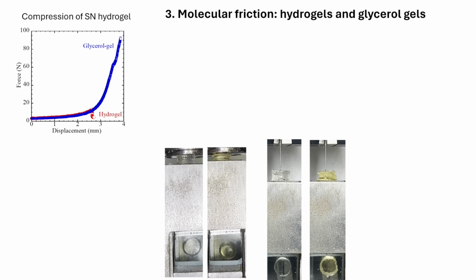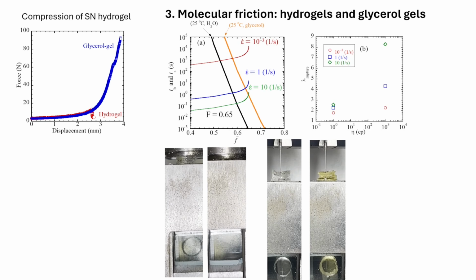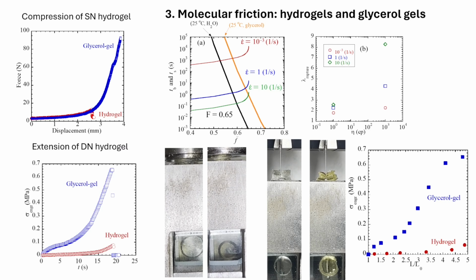So I don't have time to wait. That's the compression result, and it turns out it's indeed much more improved just by exchange. So it's already the same sample, right? Structure is already done, everything's done, boom, boom, it's just exchange. And then the next point is of course, you can do a theory, say, oh my God, if I stretch it, it should stretch more when I change water to glycerol, right? By glycerol. Here's the story, very fascinating to me.